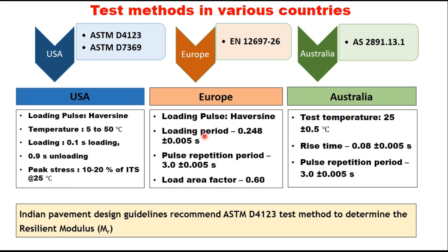In the European method, the loading period is 0.248 second and pulse repetition period is 3 seconds. The load area factor is 0.6. In the Australian method, the rise time is 0.08 second and pulse repetition period is 3 seconds, the same as in the European method.